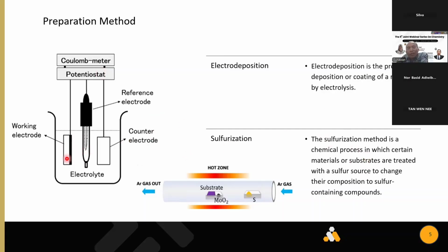After we deposit the copper on molybdenum and continue with the indium, we can say that as a stack deposition here. So we do a sulfurization here. The molybdenum covered with the copper and indium, we blow with the sulfur here, so that it becomes copper indium sulfide.